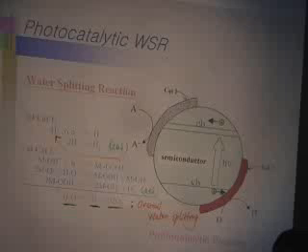And photocatalysis will play, I would say, the major role in transforming this energy system. As described by Professor Domen, you need some stringent conditions to do this job. The band gap should be large enough. In addition to this requirement, you need some overpotential to take into account the inefficiency of the processes, and also its position should be located with the conduction band more negative than the hydrogen reduction potential, and the valence band more positive than the water oxidation potential.